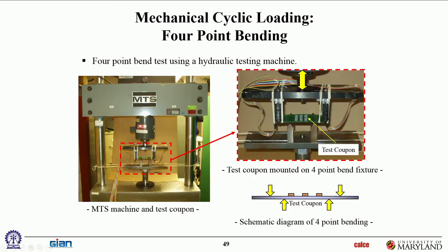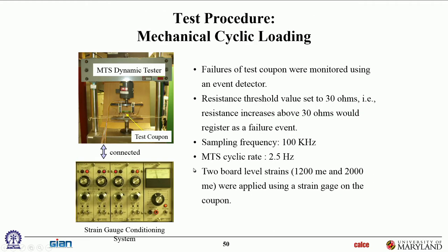So we put them on mechanical test frames, do cyclic bending. So you go back and forth. This is called 4-point cyclic bending. Ultimately, the strain solder joints will fail, and we measure the number of cycles to failure. We find out the strain levels through finite elements, and that's how we make the fatigue curves.